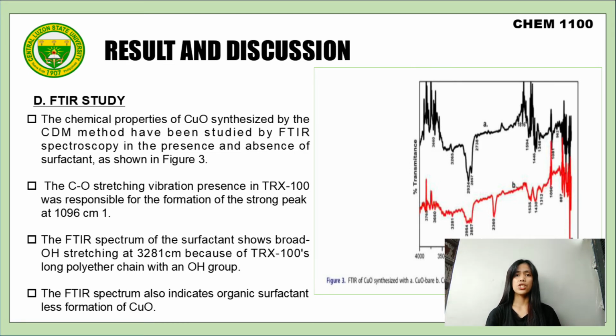The carbon-oxygen stretching vibration present in Triton X-100 was responsible for the formation of the strong peak at 1096 cm⁻¹, along with the presence of atmospheric CO2. Peaks were observed in the range of 1350 to 1700 cm⁻¹. Peaks were generated at 2900 to 3500 cm⁻¹ due to humid air and hydrated copper oxide.